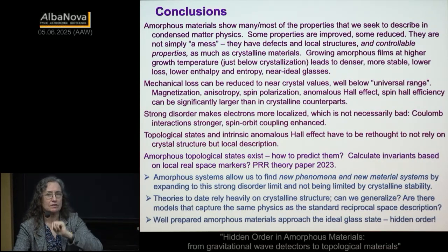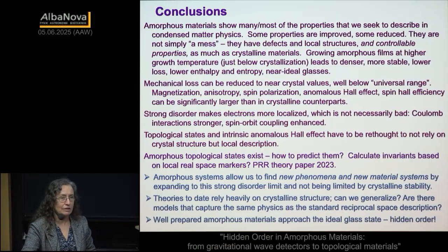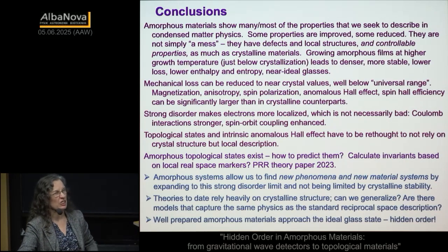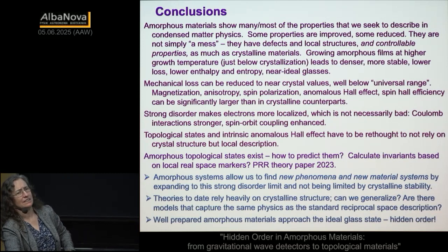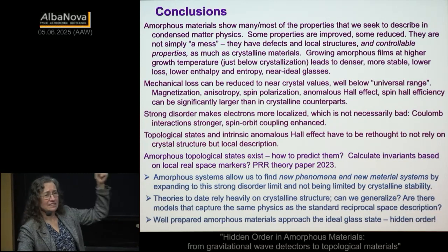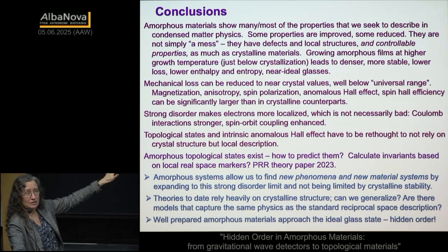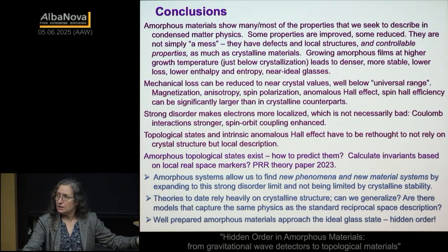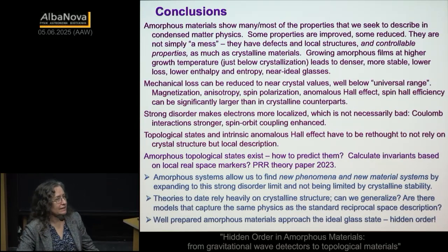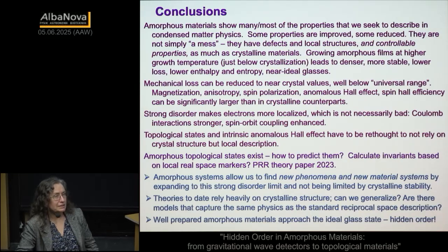So I think the bottom line on what I'm saying right now is we found that dielectric loss actually correlated with dangling bond density. And dangling bond density does not correlate with any of the things I've talked about, so I didn't really mention them. And maybe one shouldn't even be surprised at that.